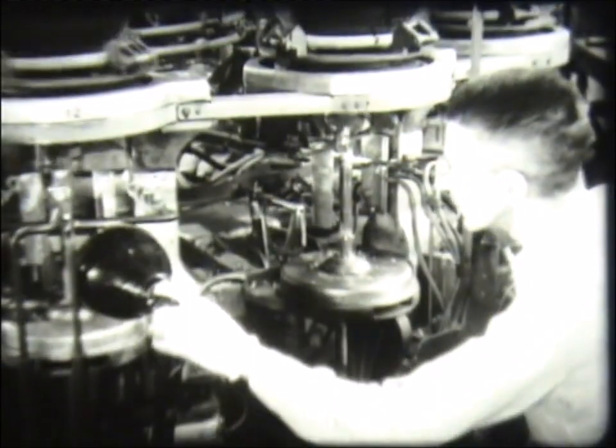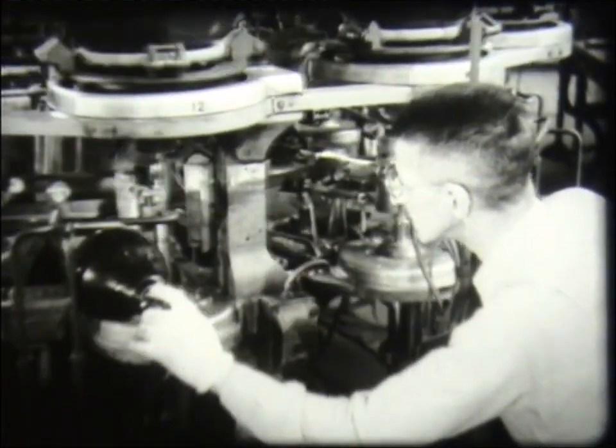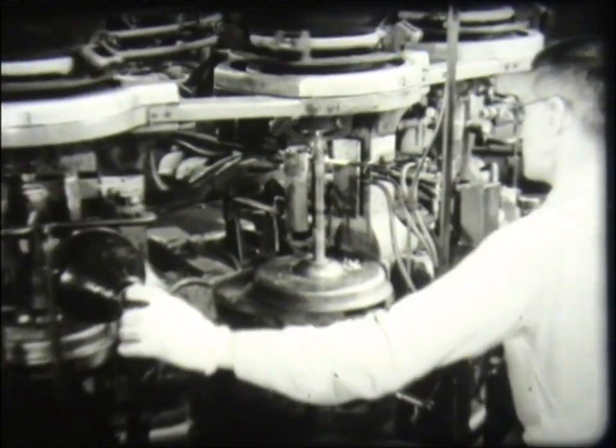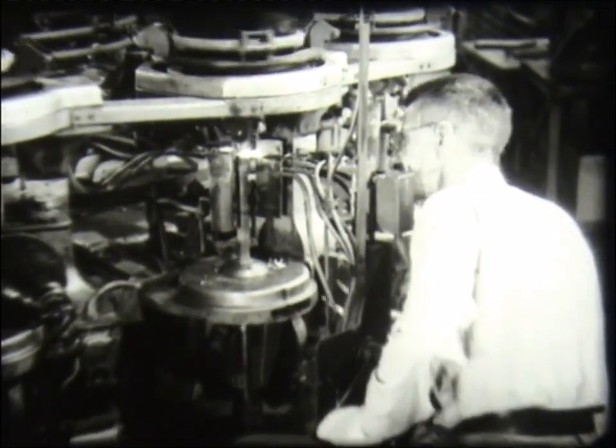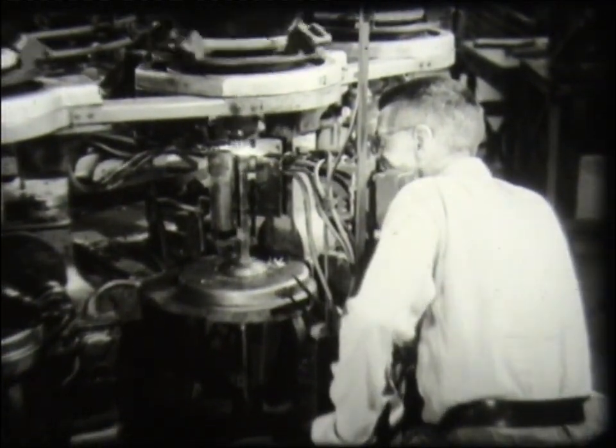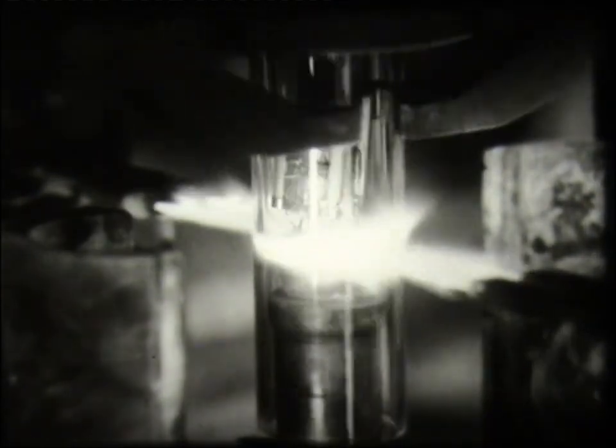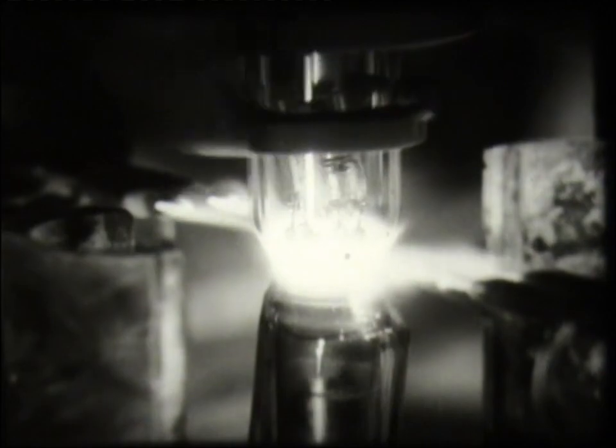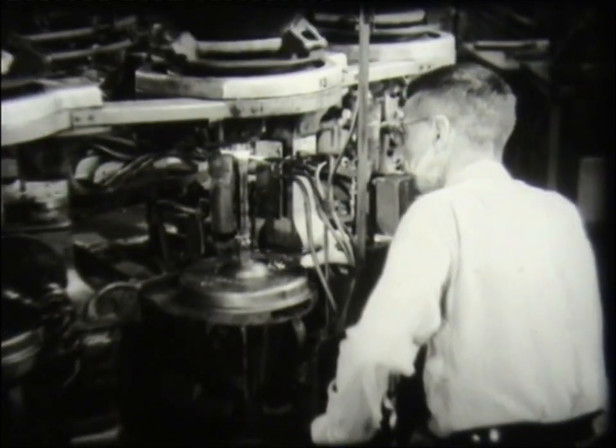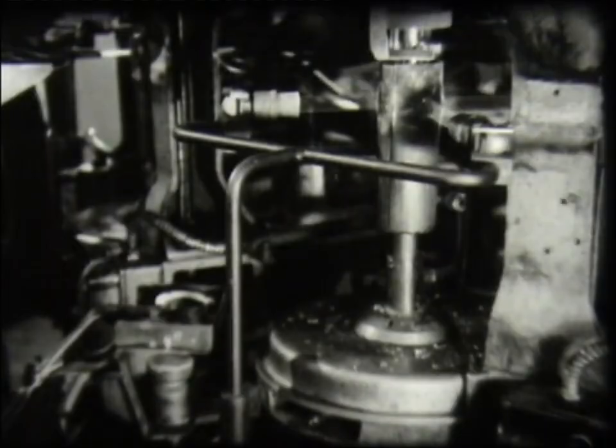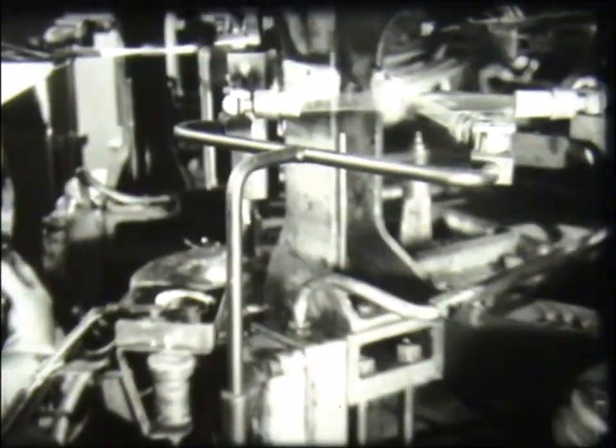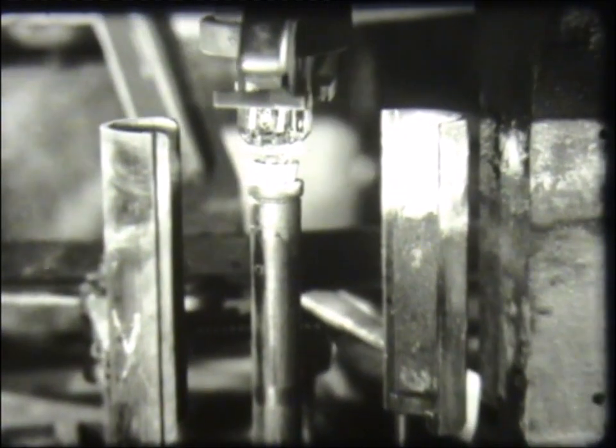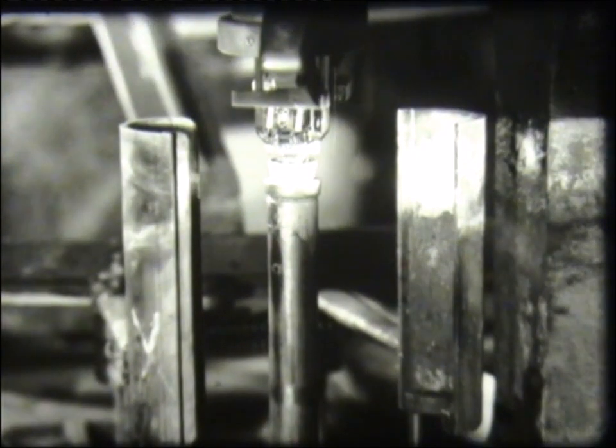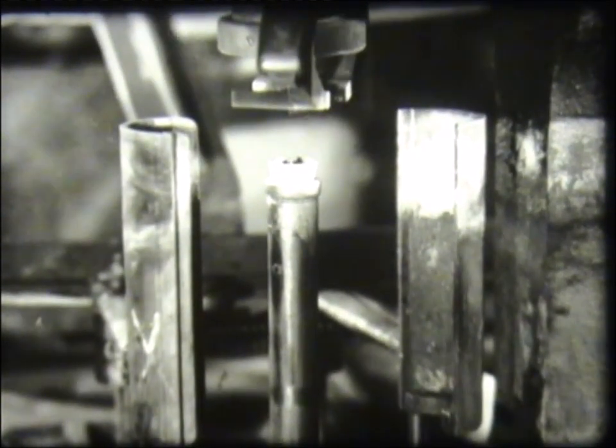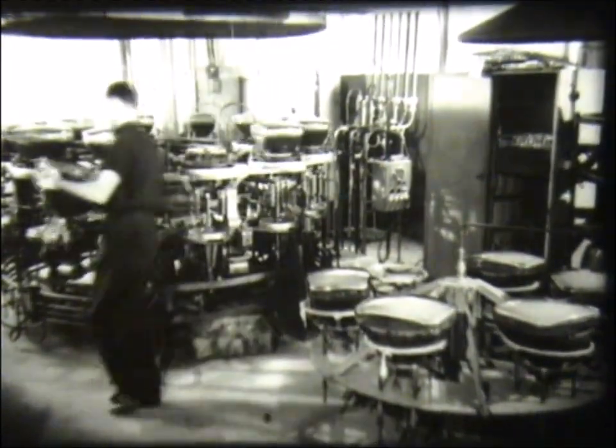As the tube rotates on its axis, it also moves to successive stations where gas flames soften the glass at the point of junction between the gun mount and the neck. As the neck and foot fuse together, the excess glass falls away. The sealing completed, the next stage is to pump the air out of the tube to form a vacuum.